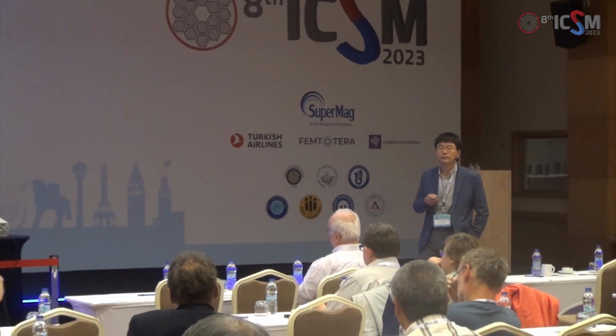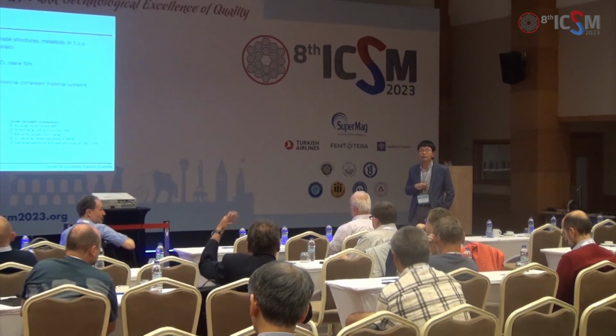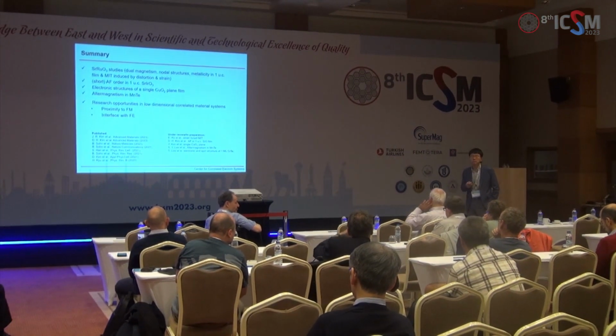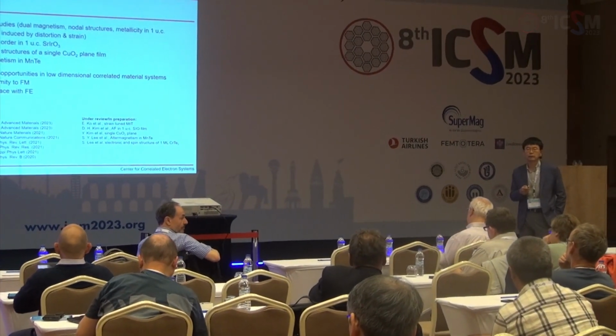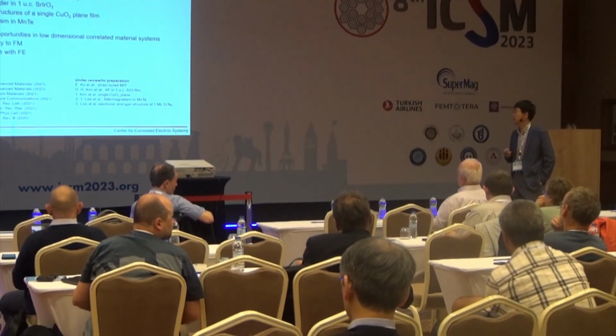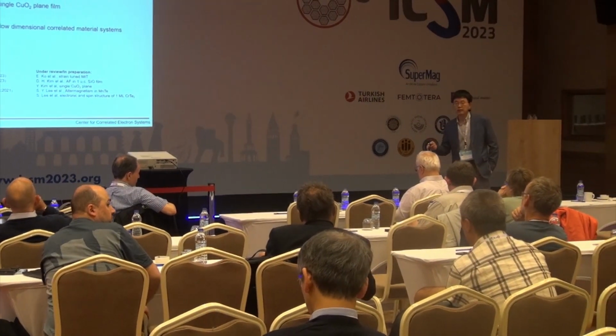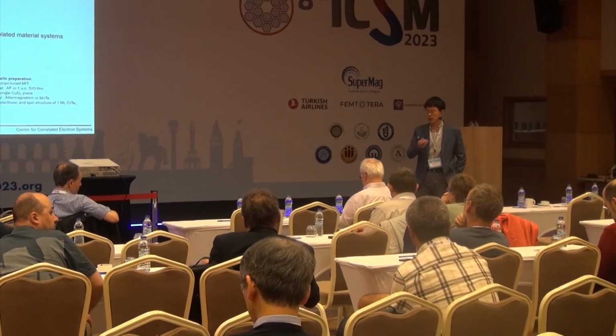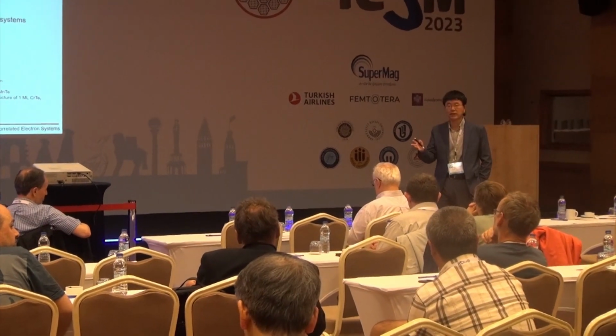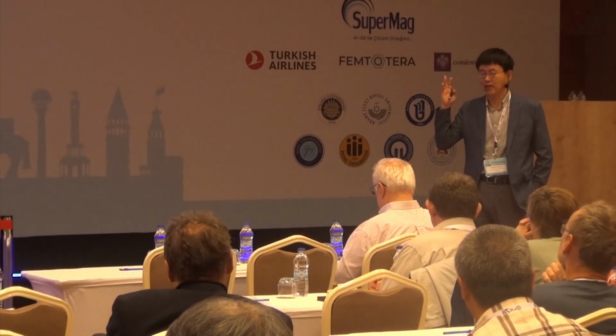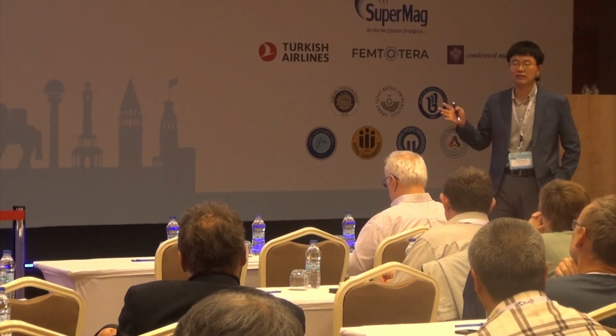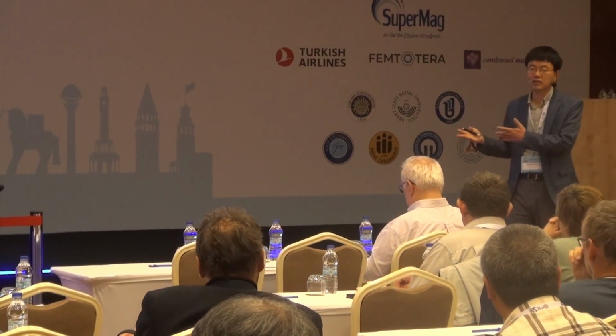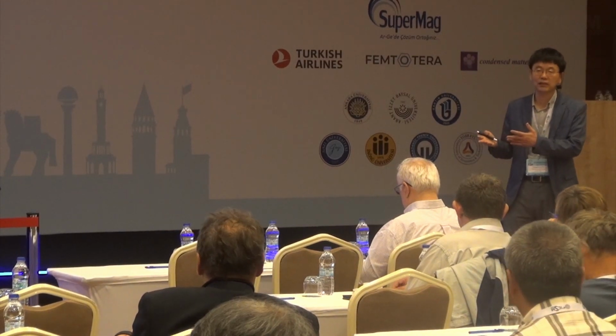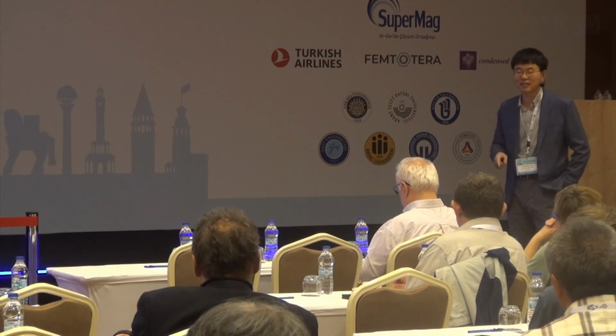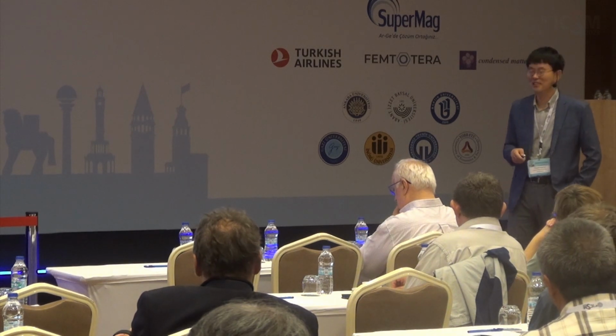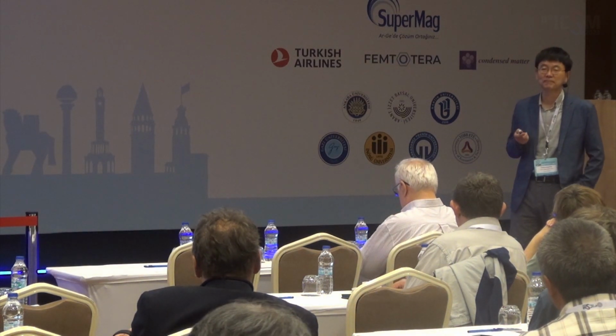What is your success rate when you do, let's say, 100 samples or 1,000 samples? What is the success rate to get a picture for the publication? Okay, so one unit cell, this is very reproducible. We found the recipe, and unless the laser goes strange or some other environment changes, that's pretty much 100%. It's very reliable, actually. Quite surprising, but I can tell you, it's quite reproducible.